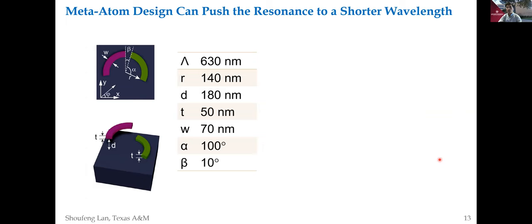Another characteristic of the chiral metamaterial is that we can tune the resonant wavelengths. We find out that the pitch, the radius R, as well as the distance between the two arcs, D, will generally determine the resonant wavelengths. The thickness of the arcs, T, and the width, W, will fine-tune the spectrum, while the angular span alpha will determine the spectrum span of the LCP and RCP spectra, while the angular separation beta will determine the spectral separation of LCP and RCP responses.